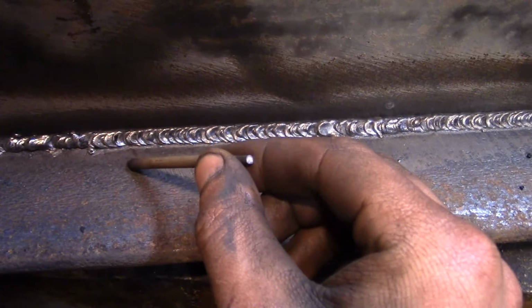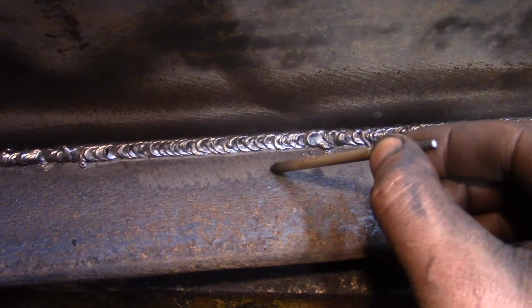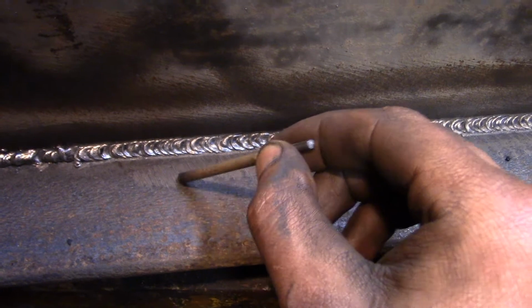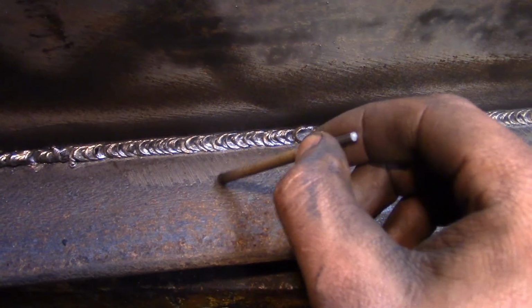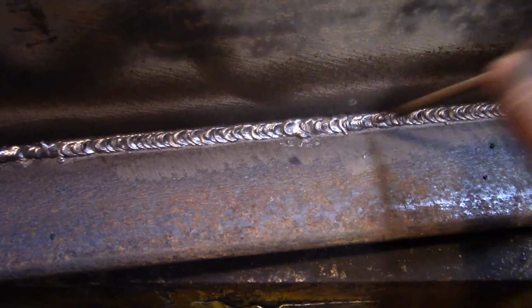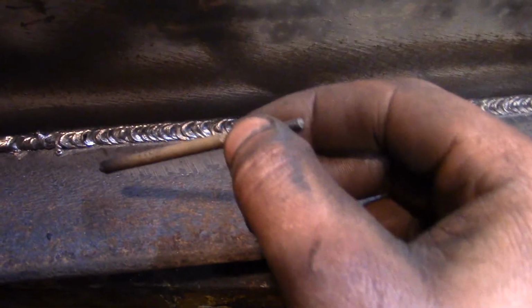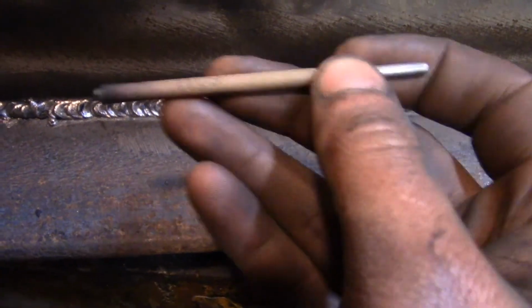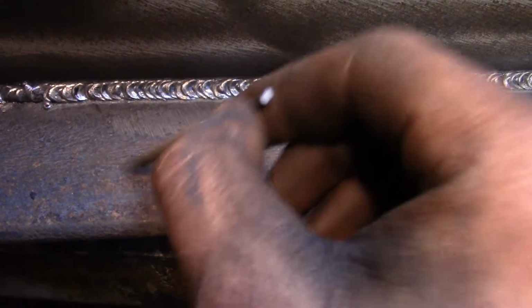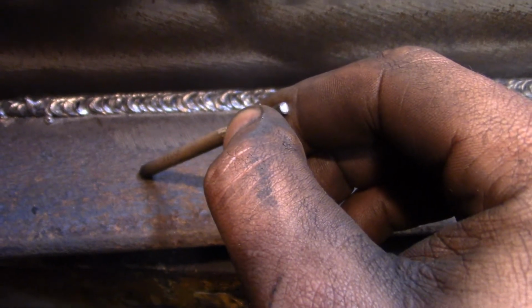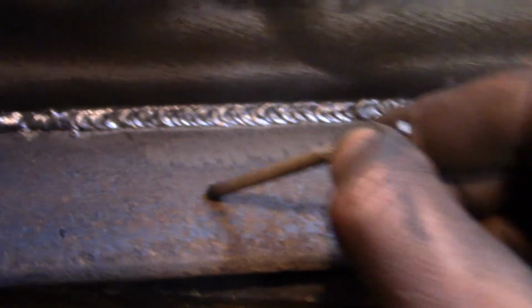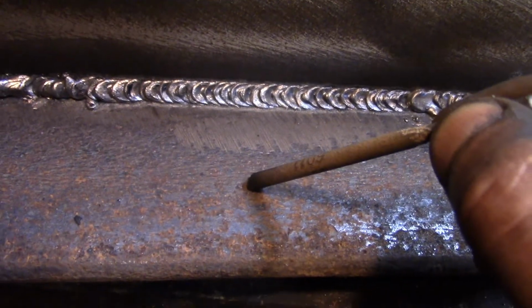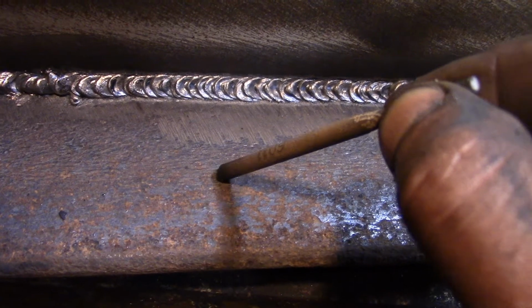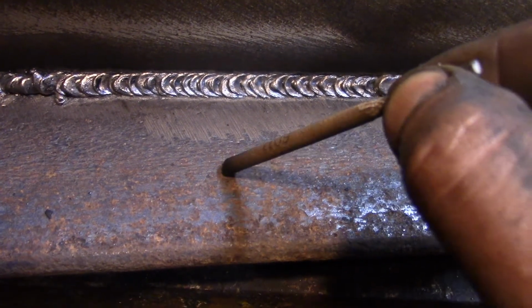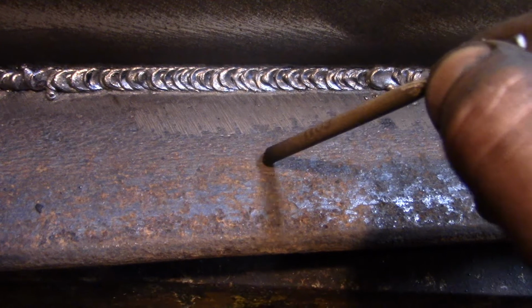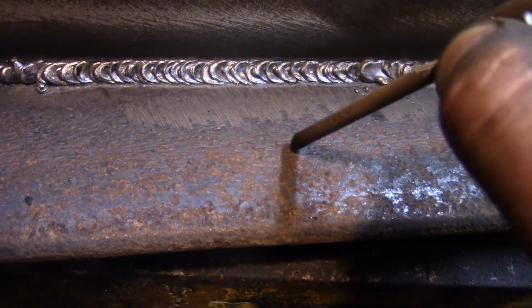Anyway, with some rods you can just drag the rod, like 7018. Some people like to do a little C shape or write their name out in cursive as they're welding. But the best thing to do with 6011 is you strike your arc and you get your weld bead going. You whip it forward about 1 electrode diameter, and then go back a little bit and hold it. Then pull it forward a little more, then back, and then forward, back. That's why they call it whip and pause. Whip it and pause.